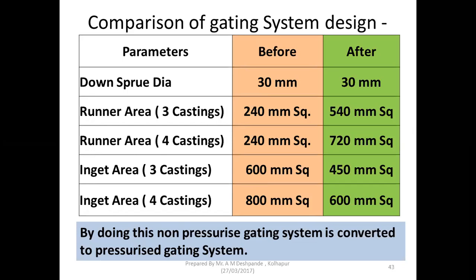So the ingate area and runner area ratio has been maintained. If you can see, the ingate area for 450 into 1.2 will be 540. Then 600 and 720. 600 is the ingate area and the runner area is 720, more than that. That's why the pressure on the ingate was there. Hence the defect has gone.